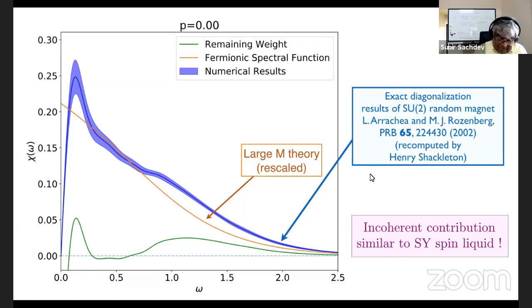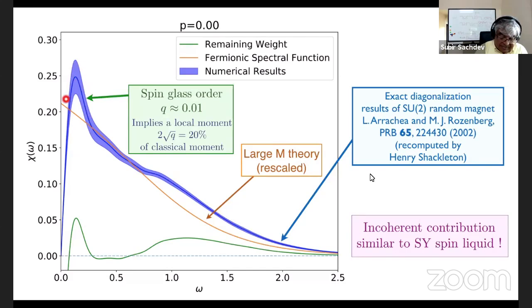But the most noticeable thing, however, is this bump here. So this seems to be an extra spectral weight at low frequencies compared to the large M limit. And that is in fact believed to be, as claimed by Arrachea and Rozenberg, the presence of spin glass order. So if you just take this little spectral weight and compute an Edwards-Anderson order parameter, you get a very small value of around 0.01. But that's not as small as it seems, because the order parameter is the square of the spin, and the maximum moment is 1/2. So the Sherrington-Kirkpatrick model would have a moment of 1/2 at T equals 0. So you have to rescale by a factor of 2 and take the square root, and that gives you something that's 20% of the classical moment.